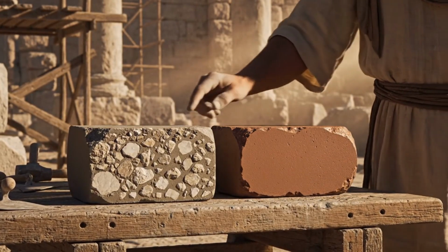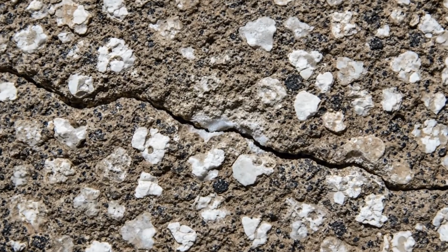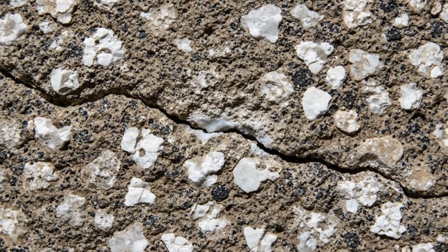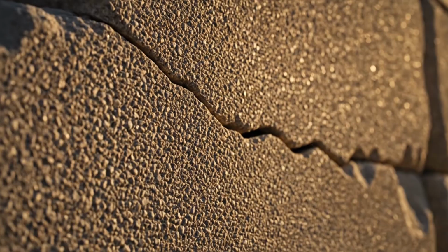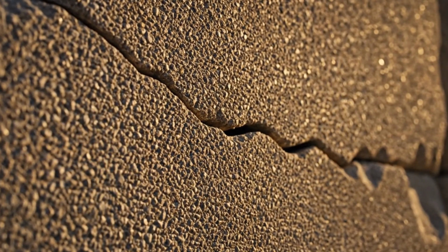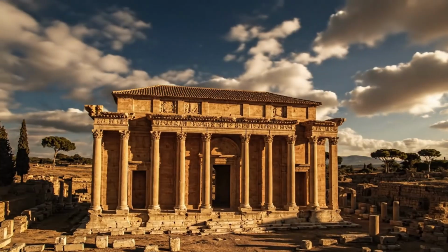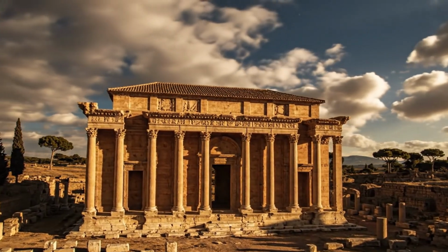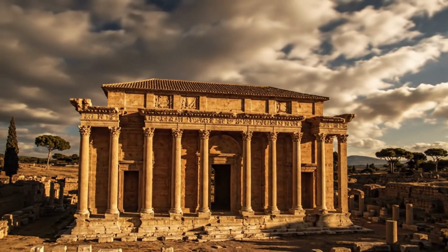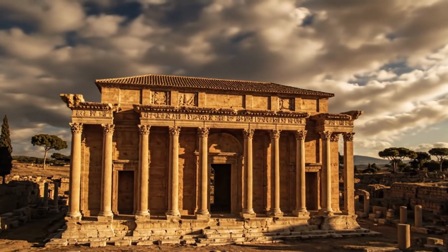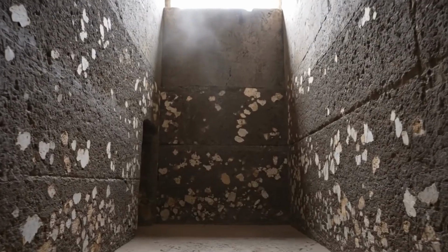These fragments became reservoirs of reactive calcium, embedded throughout the hardened concrete. Their structure made them particularly susceptible to fracture along emerging microcracks. Rather than acting as weak spots, they became strategic sites for future repair. The proposed mechanism of self-healing is both simple and elegant.